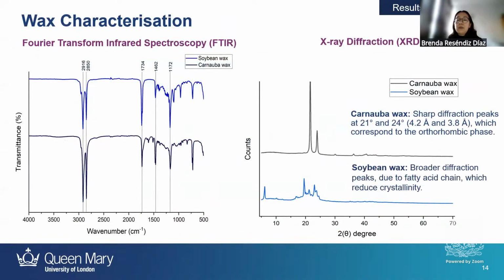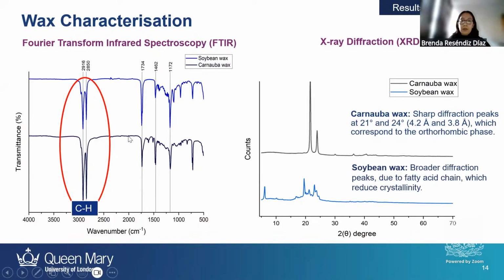Also, it was very important to see the waxes' chemical composition and also their crystal structure. So I did, again, FTIR, which confirms the CH stretching. So they are very hydrophobic. Actually, you can observe here that soybean wax and Carnauba wax have similar peaks. Actually, they have very similar chemical structure.